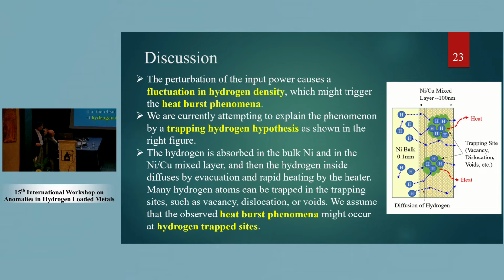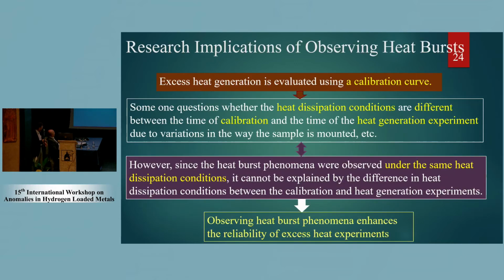Maybe many hydrogen atoms are trapped by vacancies or dislocations and voids and something like that. So we are now trying to explain the heat burst phenomena. The hydrogen is absorbed in the bulk and in the mixed layer, and the hydrogen inside diffuses through this. And many hydrogen atoms can be trapped in trapping sites, such as vacancies and other point defects, we assume. Now, that is just an assumption, but we are trying to clarify this phenomenon.